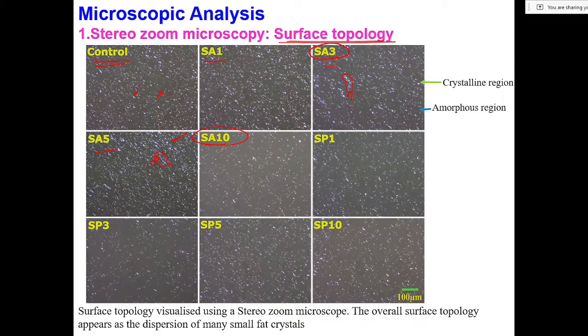So if you look into our example, what we have done is that we have added the emulsifiers at a concentration of 0.005% up to 0.5%. In this range the emulsifier content was varied, and since it was varied in such a minute concentration, this means that even at very low concentrations, the emulsifiers have the capability to tailor the fat crystal network which is being formed for the development of the oleogels.